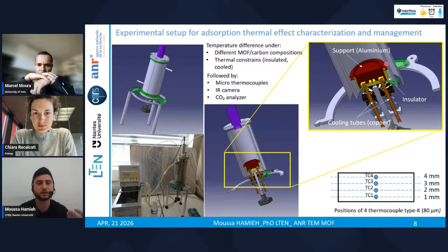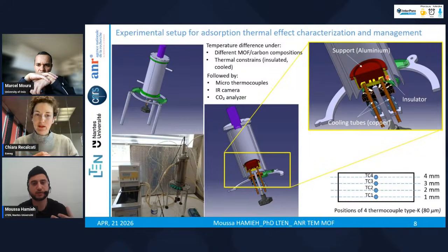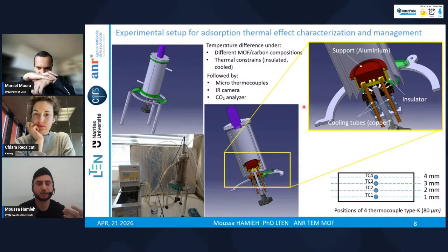In the case of insulated, we will add a Teflon support on the aluminum to work in insulating conditions, or cooled, by leaving only the aluminum support with water passing in the cooling tubes here, to maintain as much as possible the temperature during the absorption. So we'll compare everything here. Also, with this setup, we will add later, in 1 month, the CO2 analyzer. With the CO2 analyzer, we will be able to correlate the results of temperature changes during absorption with the amount absorbed for the different samples studied, when we add the CO2 analyzer at the outlet of the cylinder.